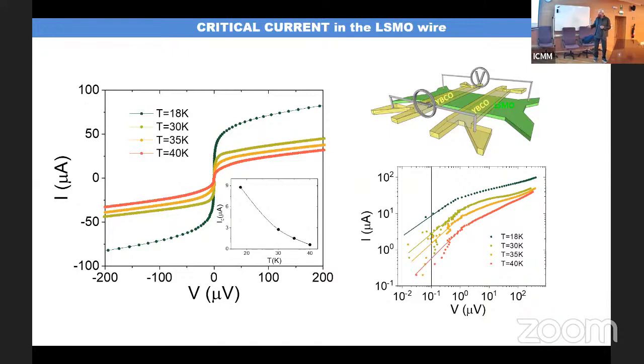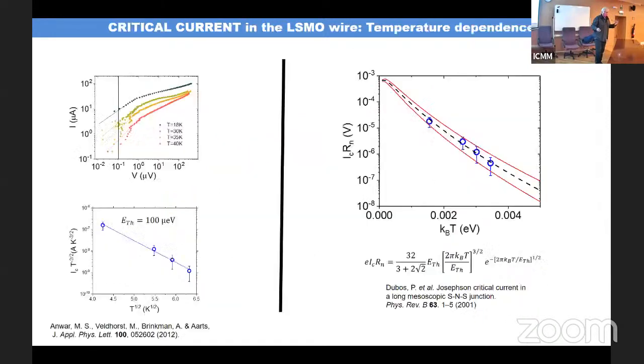So we had to use a very, very ambitious voltage criterion to reach the nonlinear regime of the critical current and the IV curves. This was challenging to measure. So the first question is whether these values of the critical current that we're getting are realistic, do they make sense or not? Because having such a long weak link in a ferromagnet opens a lot of doubts. So we analyzed this critical current in the framework of the SNS theory,